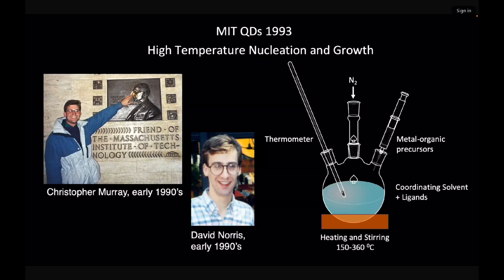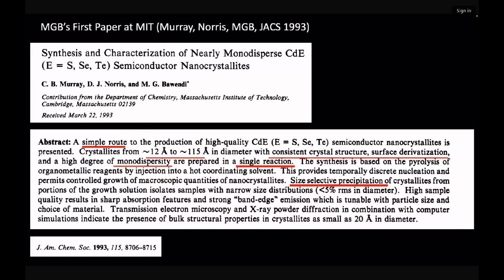You've separated nucleation and growth in 2 steps, and then it slowly grows in the presence of ligands that protect the surface as it grows. And you control it. And this is a very simple idea, right? It's really simple. But it turns out that simple is sometimes really important. Okay, and so then we wrote a paper. This was my first paper at MIT in 1993, so for 3 years. If you have an assistant professor that doesn't produce any papers in 3 years, you think, this guy's going to fail, right? Something's really wrong.